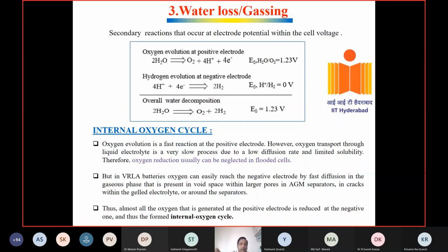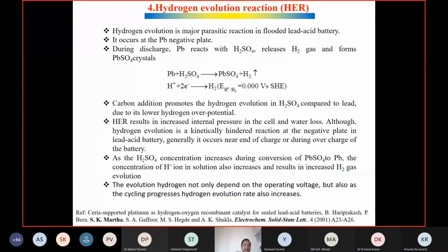I already told you oxygen evolution and hydrogen evolution in the lead acid battery can together cause water loss, and grid corrosion also causes water loss. So in the past, we developed platinum catalysts to do oxygen and hydrogen recombination inside the cell. Again, this has to be done in a systematic way to combine the hydrogen and oxygen, because in the VRLA cell only a little hydrogen and oxygen is involved, only when you go to high voltages. So this is another area you can also focus on. Those who are working on catalysts can work on how we can develop catalysts for hydrogen and oxygen recombination inside the cell of a lead acid battery.